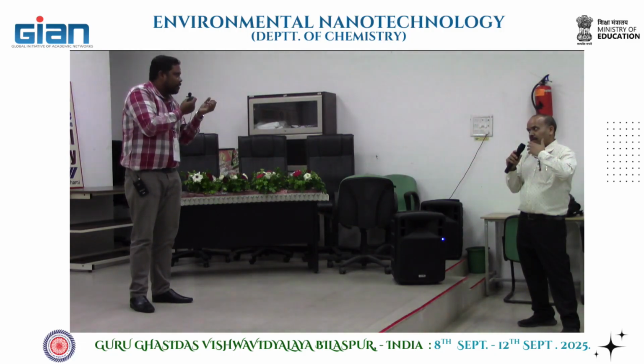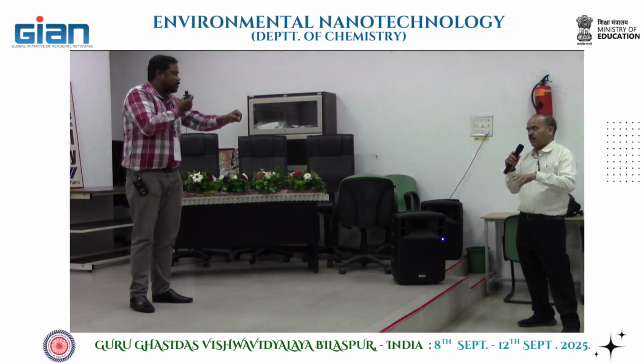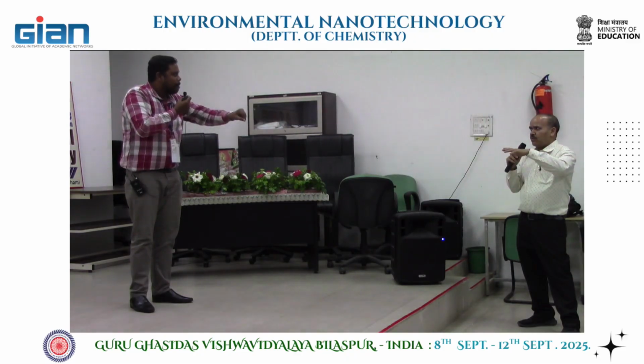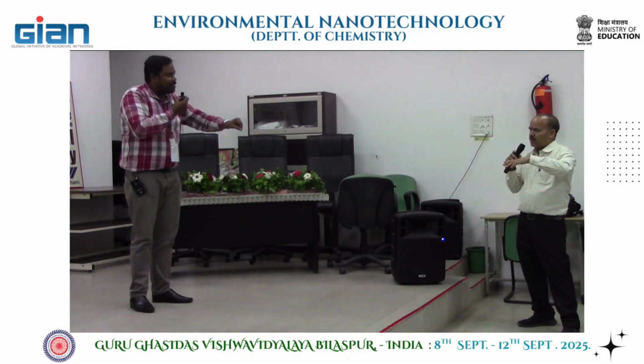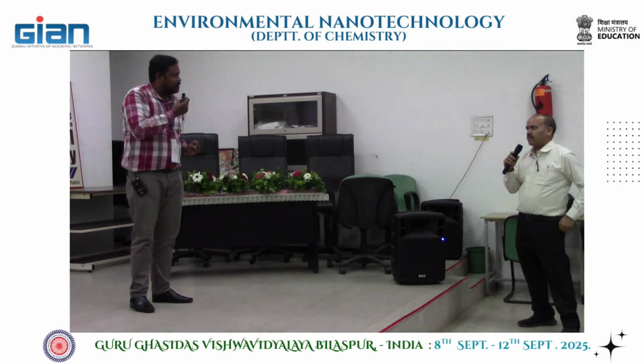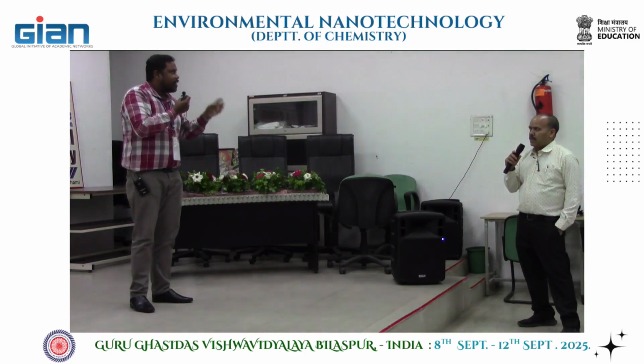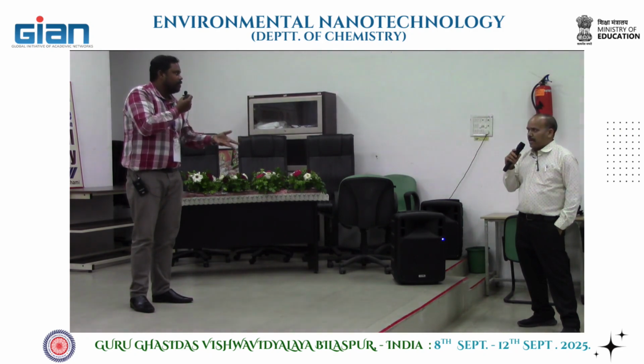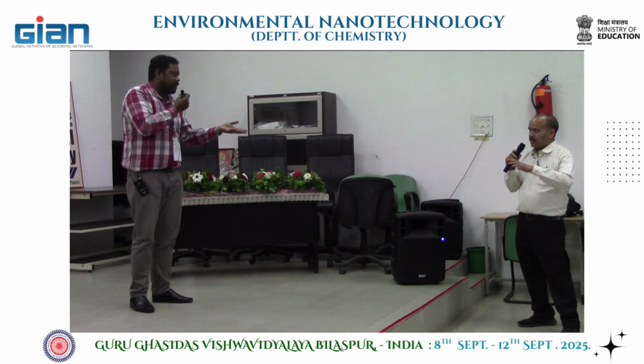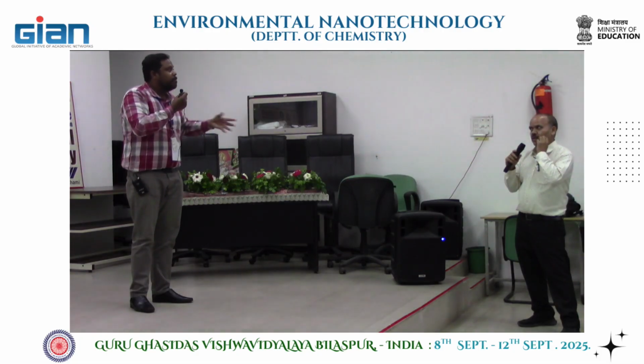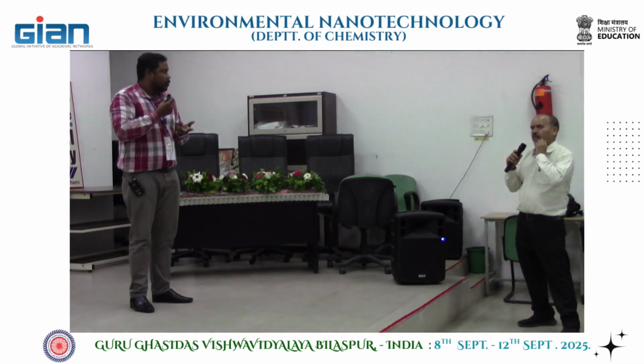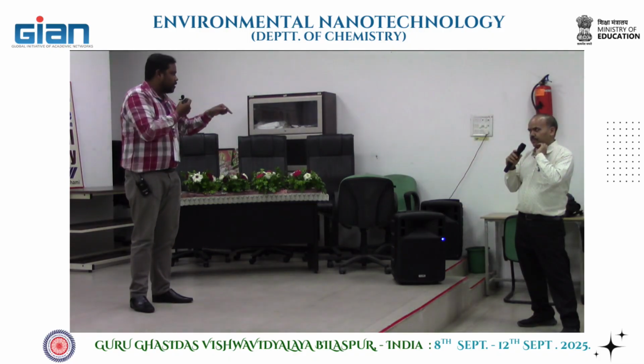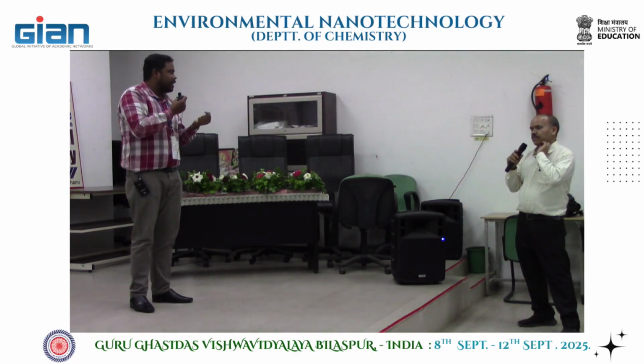We are focusing on thermodynamic parameters. If the most stable cage forms at room temperature, sometimes 60 degrees centigrade, not very high, but we are giving time. If kinetics were important, then it would give a mixture of products. So we are trying to make the thermodynamic parameters work. Then only we'll get a single unit.